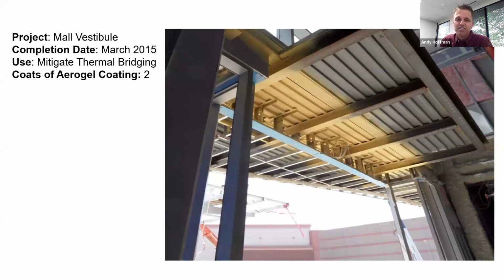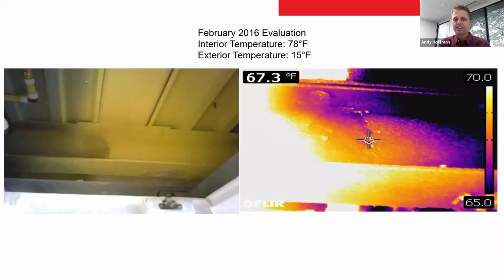And Minnesota, obviously, very cold. They're pumping a lot of heat in this vestibule to make it a comfortable space because it's a pretty good size. So you notice in this case, we did not only the beams themselves, we also did the underside of the deck as well. And this is one, again, where I had the thermal imaging camera to go in, kind of take a look at the impact that the coating had on the surface temperature in relation to the areas that didn't get it. So right before this building was getting buttoned up, we were in there in a February time of year.